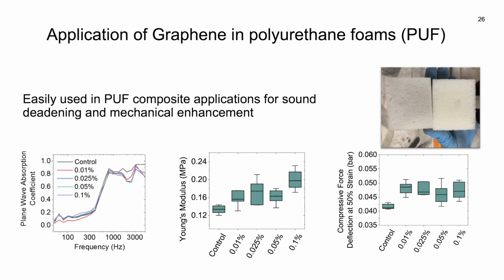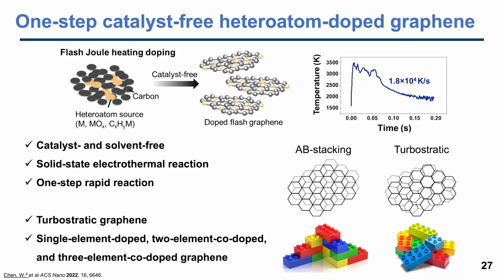This is not taking a plastic and recycling it, where you would lessen the molecular weight. This is totally breaking every carbon-carbon bond in it and letting it reassemble. So that's how this is an environmental application. We can add different heteroatoms to the graphene. So what you can do is take the graphene, add these different heteroatoms to it, and then flash it. Or you can take flash graphene, add heteroatoms, and flash it again, say to 1500 degrees. And you can make these doped graphenes this way.